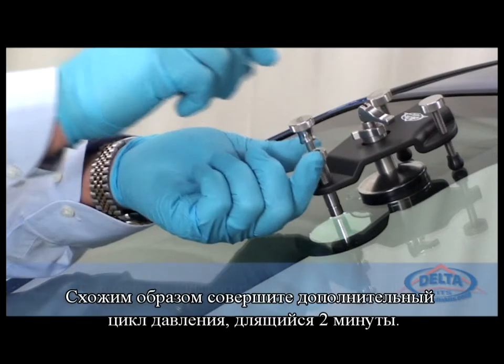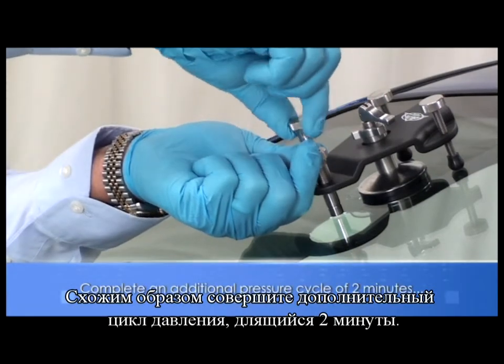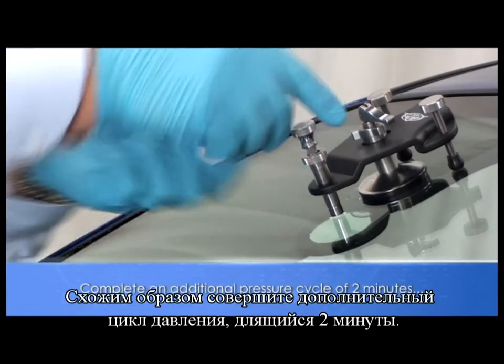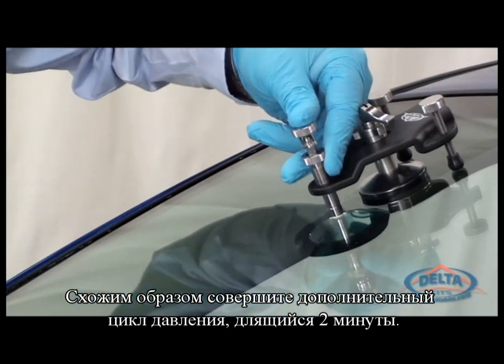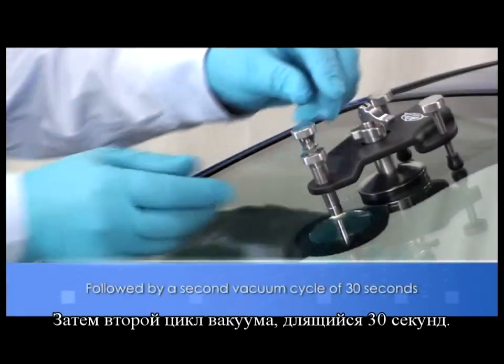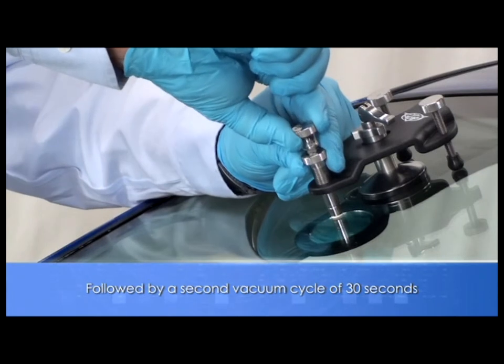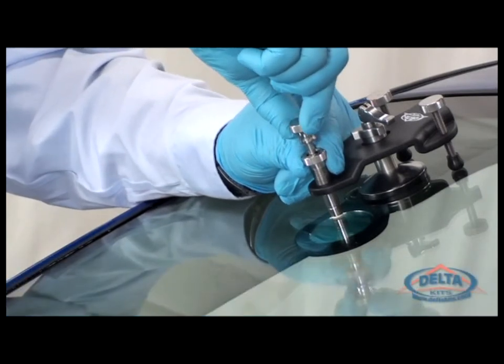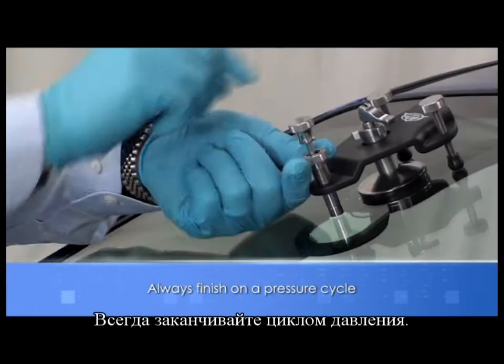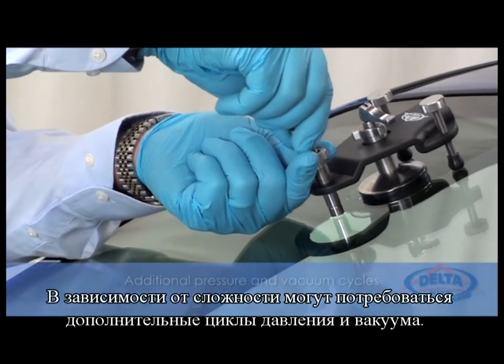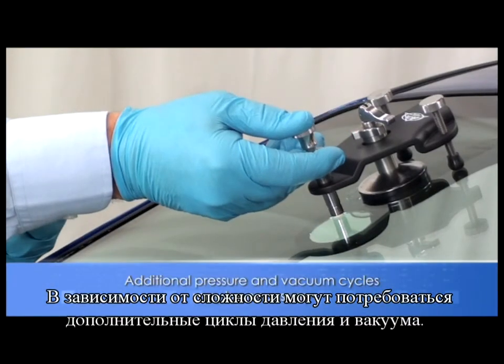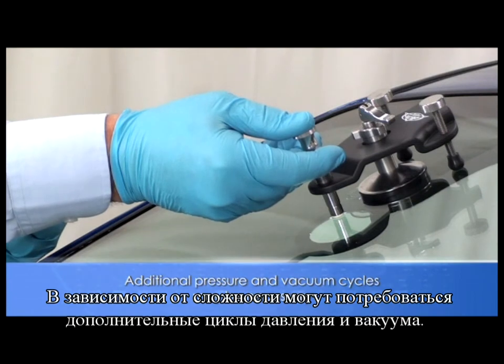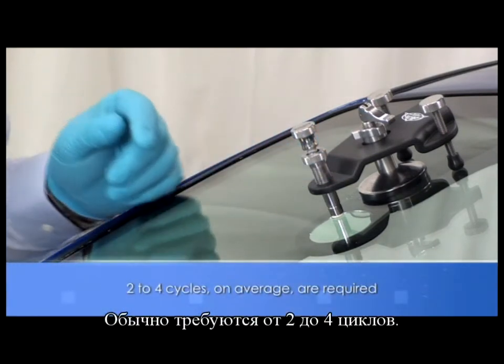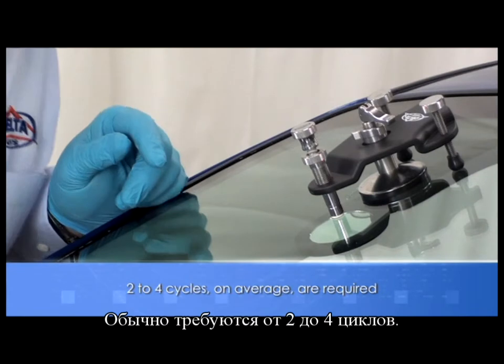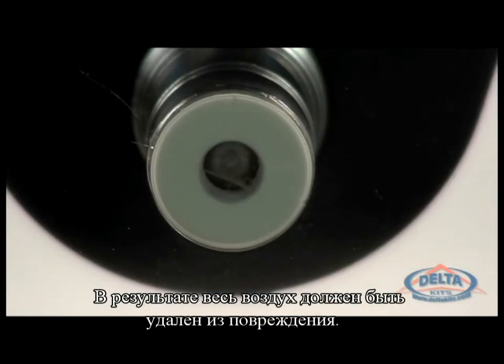Using the same techniques, complete an additional pressure cycle of 2 minutes, a second vacuum cycle of 30 seconds, and always end on a pressure cycle. Additional pressure and vacuum cycles may be necessary depending on the complexity of the break. 2 to 4 cycles on average are required. The end result should be that all of the air has been removed from the break.